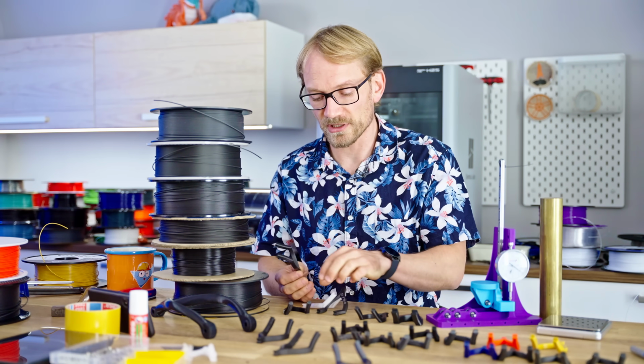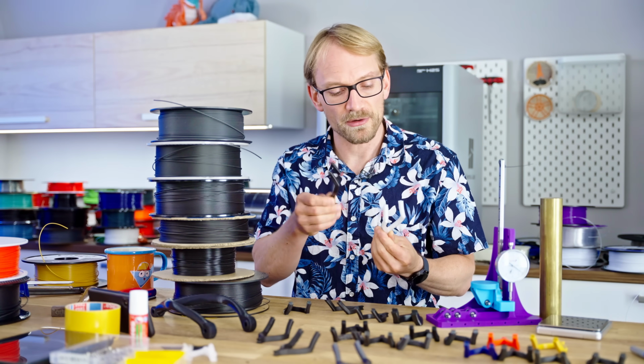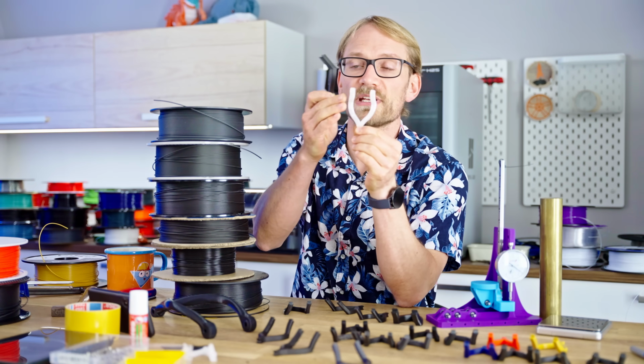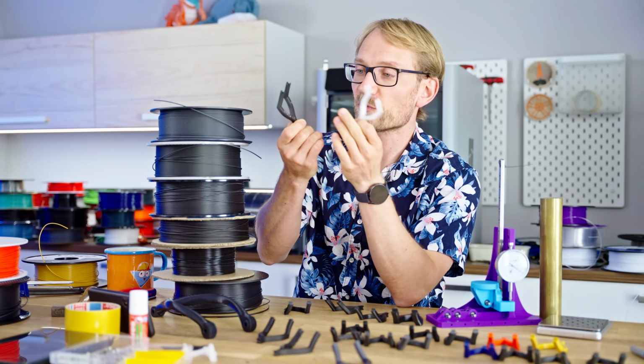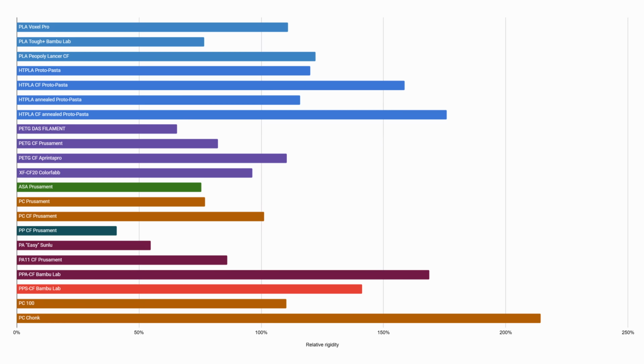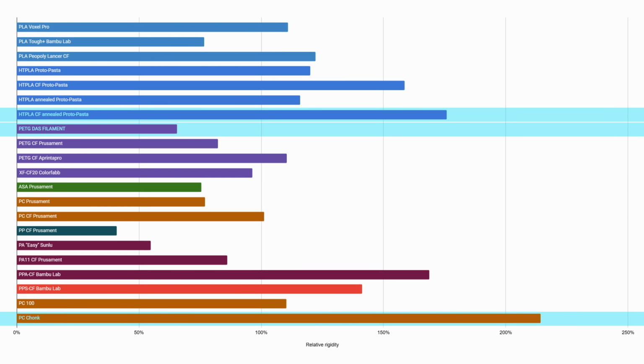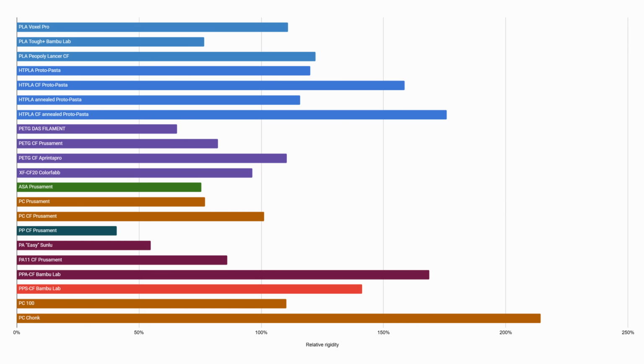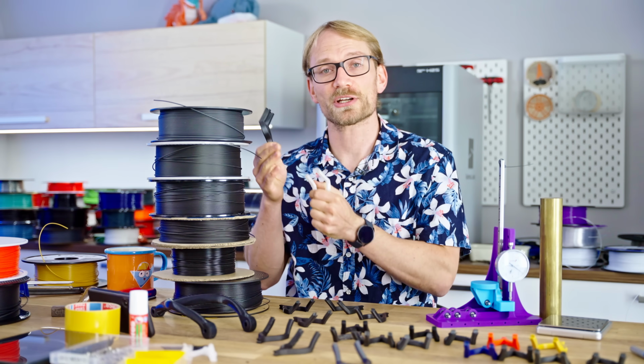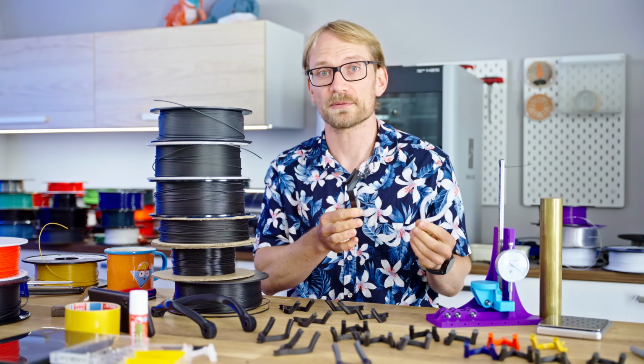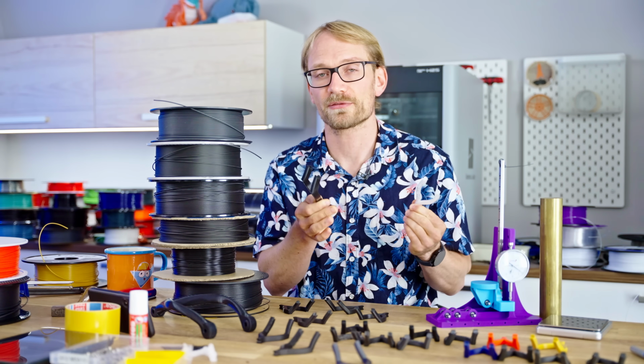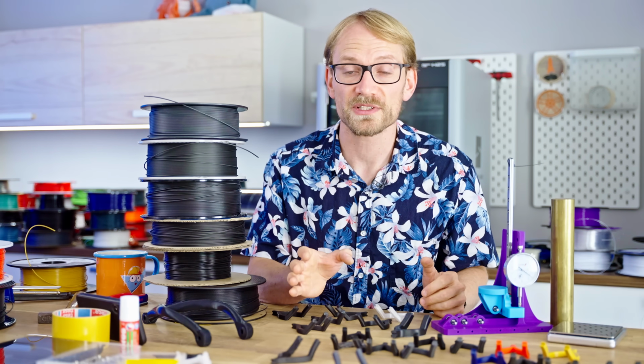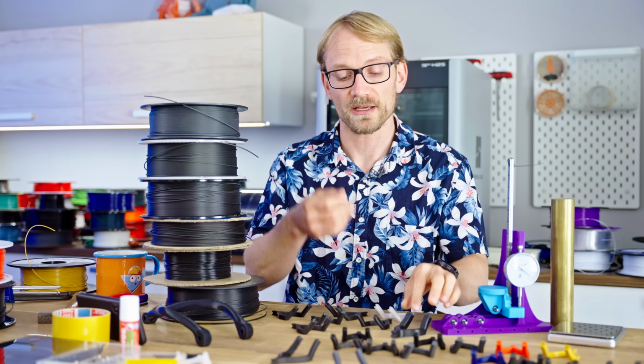But the difference really is just about a factor of 2x from PETG to the temperature-treated, heat-treated HTPLA-CF. So that is about 2x. This one bends half as much as this one. However, this chunky one bends 1/3 as much as this one. So just with a small geometry change, you can much improve your part's rigidity without opting for a higher end filament.